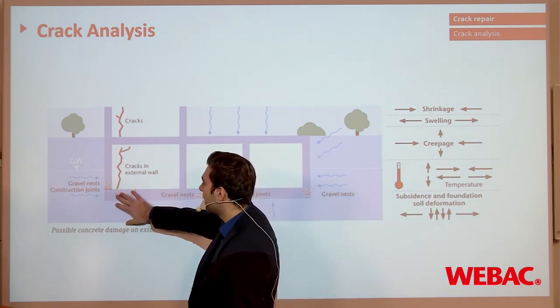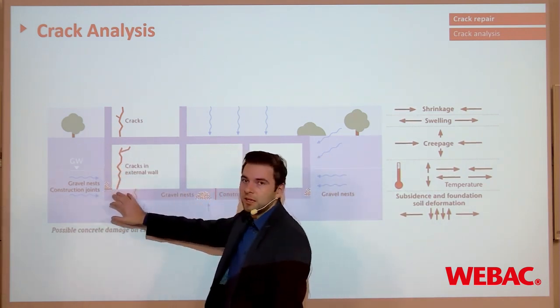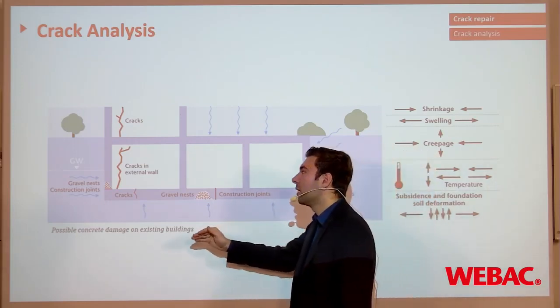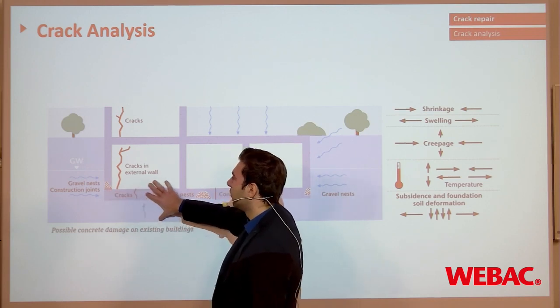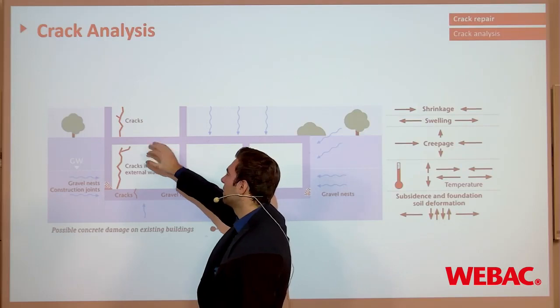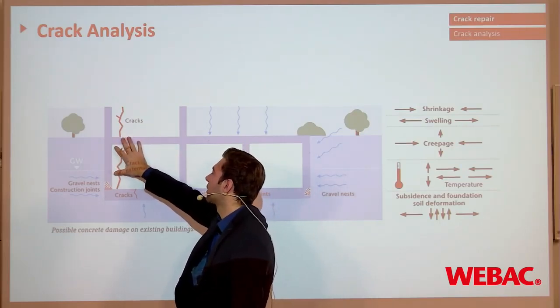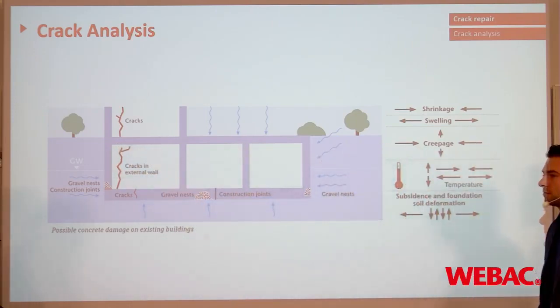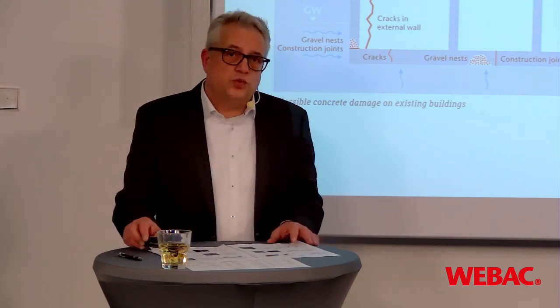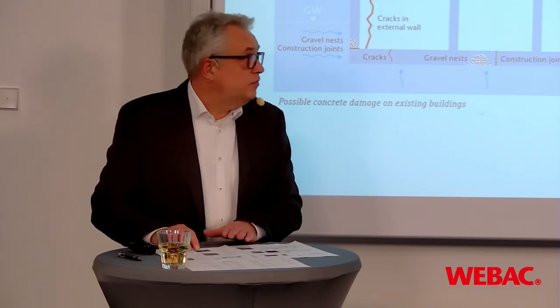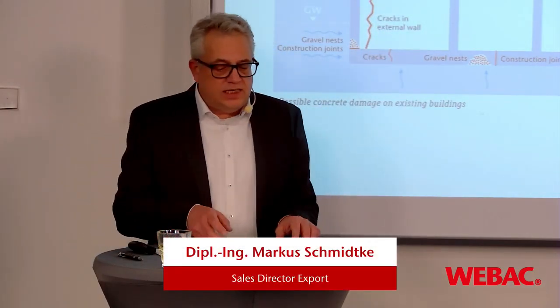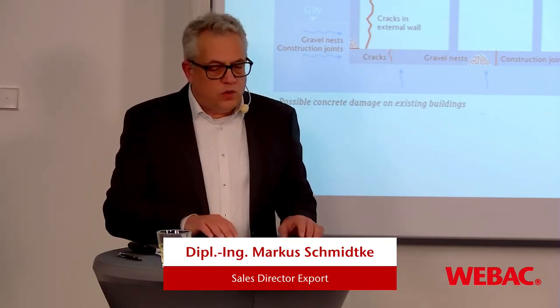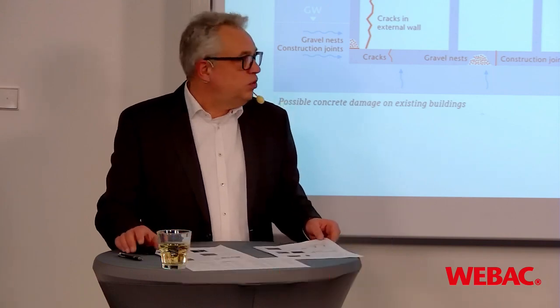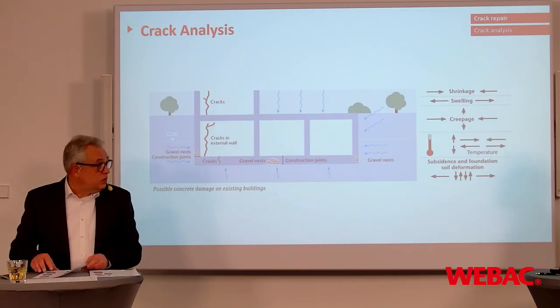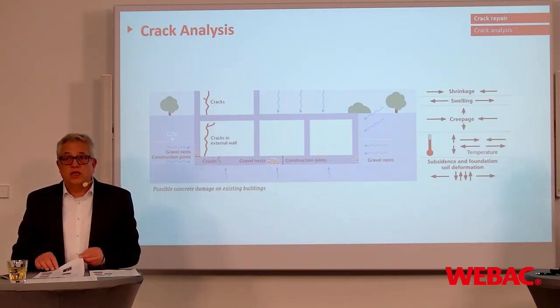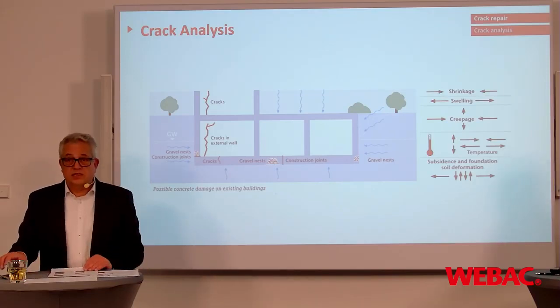Once again, the connection of bottom slab and wall, the construction joint there, or especially when we are talking about basements and you probably are below groundwater level, there you can have the influence of water. Or if you're above groundwater level, then we are probably talking about dry cracks here. The point is also, due to the shrinking of the concrete, you will mostly receive separation cracks in the wall. And these separation cracks will go through your whole concrete, meaning the reinforcement is also exposed to water. And this can also cause corrosion of the reinforcement. And for the lifetime of the building, this is a big issue.